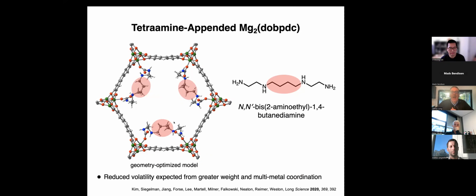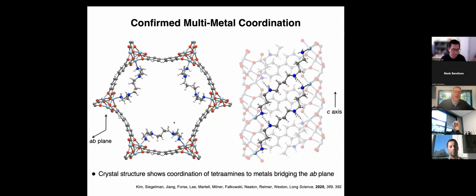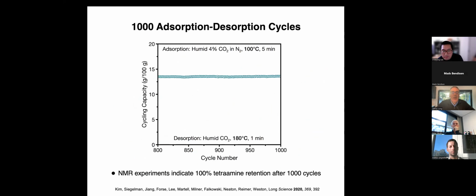And excitingly, these tetraamines, when you load them into the MOF, they actually organize themselves. And so you can get crystal structures showing how they're organized. And so here on the right is a top view. You can see each tetraamine is bound to 2 metals instead of just 1. And there's even some hydrogen bonding between tetraamines. And so these materials can be really effective.